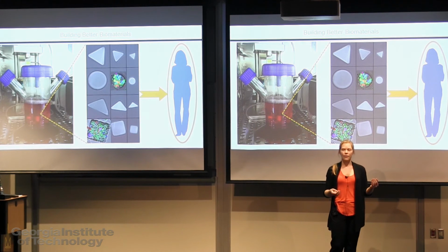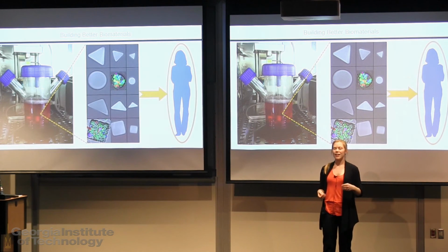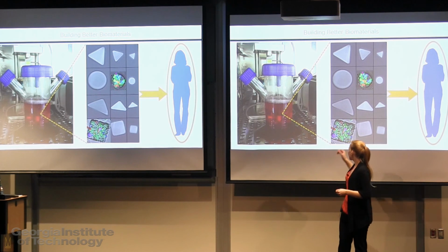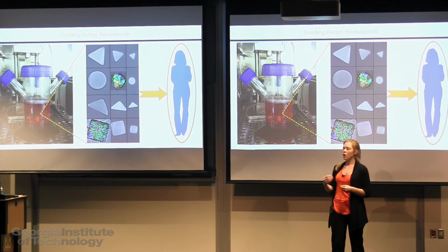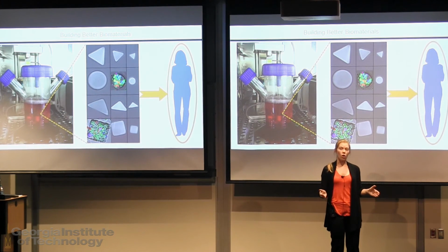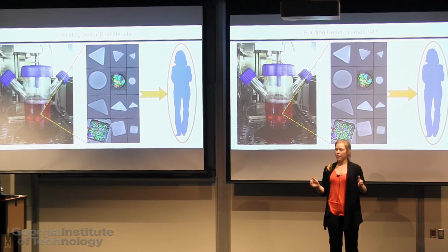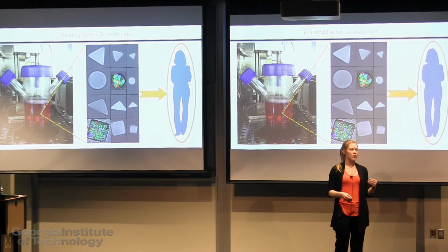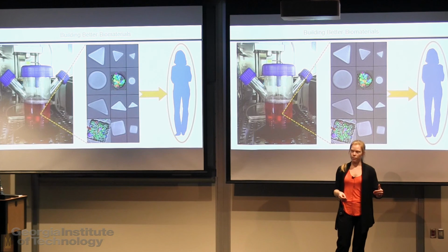Through Emory, I have access to an imaging machine that can collect data on thousands of microparticles each second. So I designed these size and shape barcodes along with an image analysis platform to read them that automatically distinguishes all of my different biomaterials. Then, using fluorescence data that it collected at the same time, I analyze how the cells responded to that biomaterial.